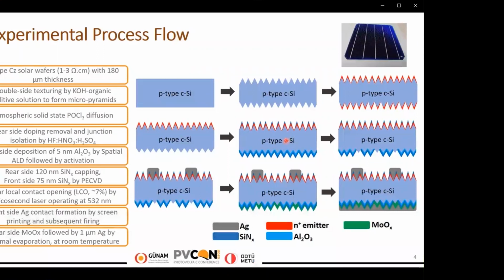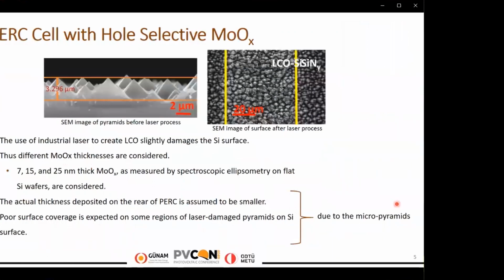The rear side is passivated by 5 nanometer aluminum oxide, followed by activation annealing and silicon nitride capping. The front side anti-reflective coating, silicon nitride, is also deposited by PECVD. Local contact openings were made by picosecond laser at the rear side, with approximately 7% of total area. Silver front contact formation is performed by screen printing, then rear side molybdenum oxide and the following silver are deposited by thermal evaporation at room temperature. You can see the SEM images of rear side micropyramids before and after laser processing.